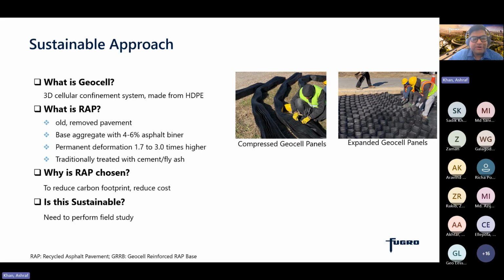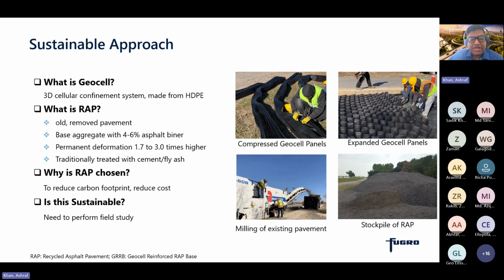And the next question is, what is RAP or recycled asphalt pavement? This is basically the old pavement. When it reaches the end of life, we mill it and store it in a nearby stockpile for future use. It is basically aggregate with 4 to 6% asphalt binder. And we know we had the issue with RAP that it has 1.7 to 3 times higher permanent deformation compared to the flex base material. Traditionally, it is treated with fly ash or lime or cement.